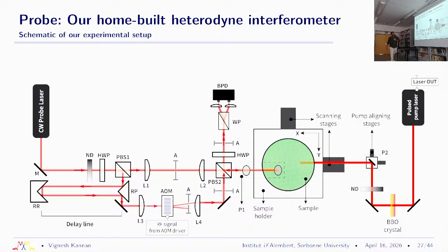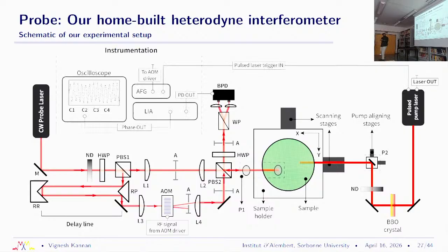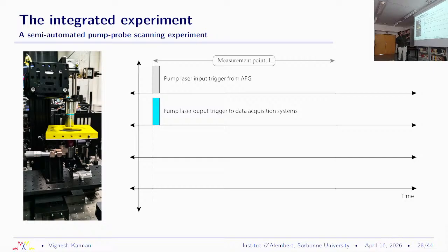I use that to measure the displacement of my point. For a single measurement of a wave on this film, I would do something like 100 pumps at the exact same point on my sample, and I would scan my sample so that I make measurements at multiple points. And I put all of these together and I build my full wave profile. So just to give you an idea of the experiment, this is just one cross section. What you see here is a microscope objective. The pump beam, which is the pulse laser source, goes in and excites the back surface of my wafer. The wafer is simply mounted on XY stages with a 3D printed holder. That microscope objective goes to the other side, where I have my entire interferometer to make measurements of the wave in my system.